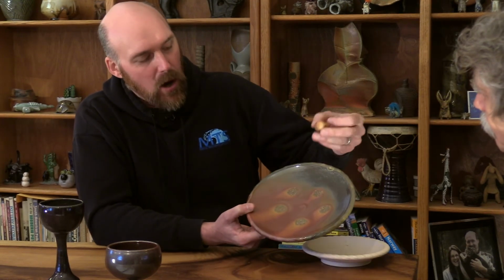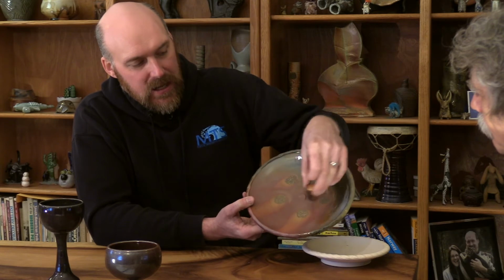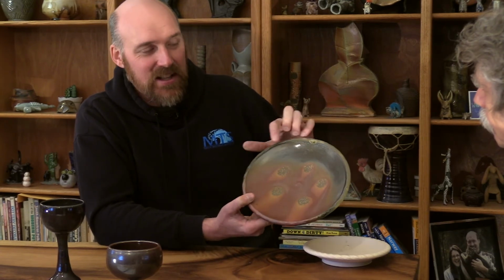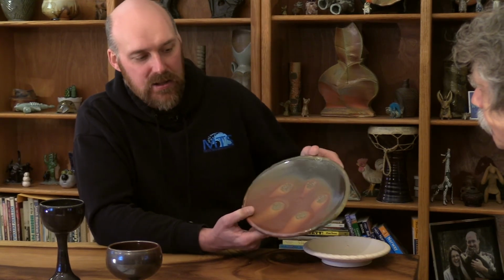So the piece went in the kiln looking like this, and then these wads were glued to the piece like this, and then it comes out of the kiln like this. And so there's a lot that we're doing on the outside of the kiln, but there is no applied glaze on this piece, it's chemistry between the wood ash and what's existing in the clay. Different types of clay, porcelains, stonewares, they will produce different color palettes, and so there's a huge number of variables in the process. I can use the same clay and fire it in the same kiln, but if I fire it in a different location within the kiln, it'll look different. And that's if everything else is the same.